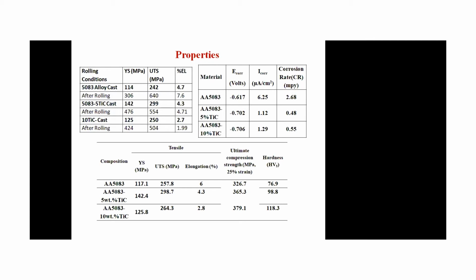So that can be proven: if you add very fine particles into the simple alloy you have deformed, then the yield strength only increases up to 306, because any reinforcement acts as a pinning site for the deformation. So very fine grains will generate because of the reinforcement, because when you do hot rolling, there is simultaneous recrystallization and recovery going on. And after recrystallization, new grains form. So this ceramic part acts as a pinning site for new grains.